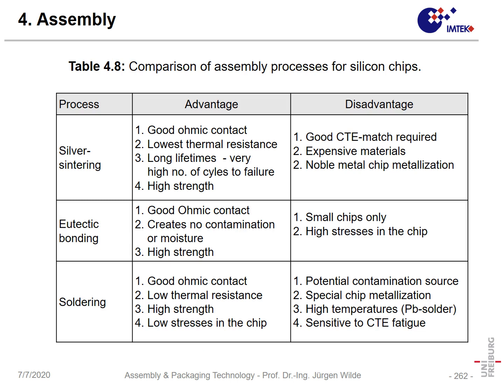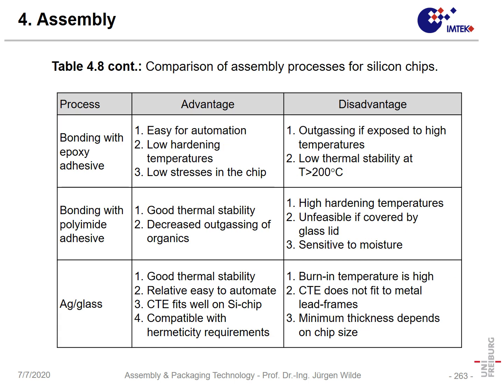Again, when we look at the individual advantages, for instance, silver sintering has long lifetimes, high strength, and what is most important, lowest thermal resistance. Eutectic bonding has a good ohmic contact, high strength, but it leads to high stress, and not all chips like it. Soldering has a good ohmic contact, has a low thermal resistance, high strength. Also, it's cheap, but you cannot get the ultimate properties like you can get in silver sintering. So often for very high performance applications, silver sintering is preferred.